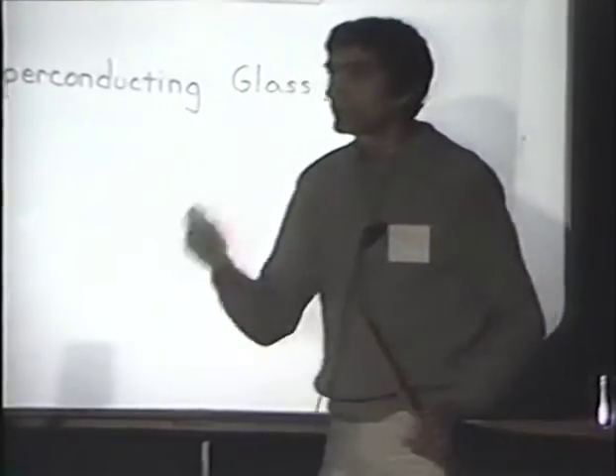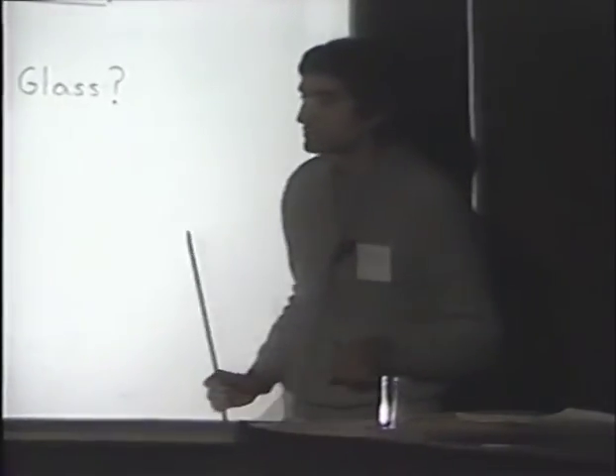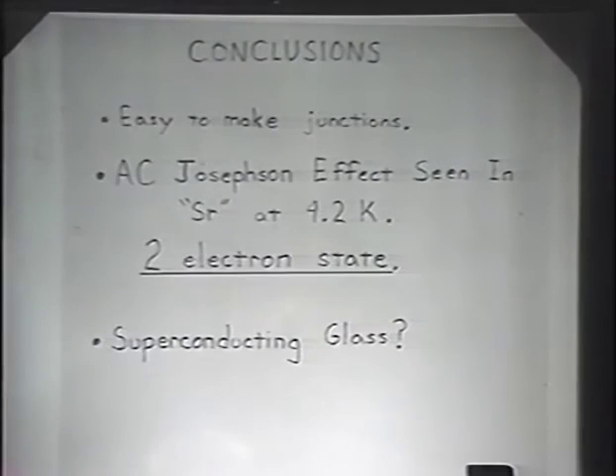Finally, just to conclude, it's very easy to make junctions in this system. We basically see them every time we cool down. We've seen the AC Josephson effect in the strontium compound at 4.2 Kelvin, and it's a 2-electron state. And we might be seeing some sort of superconducting glass. Thank you.